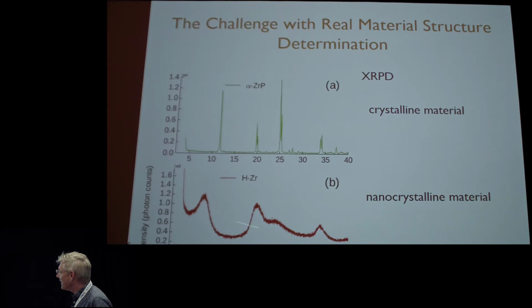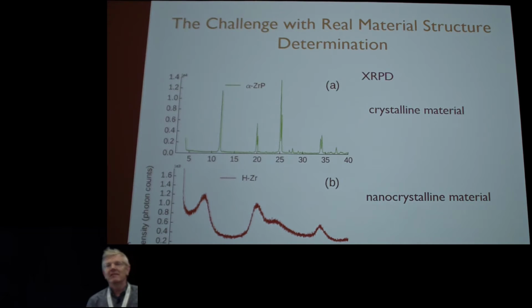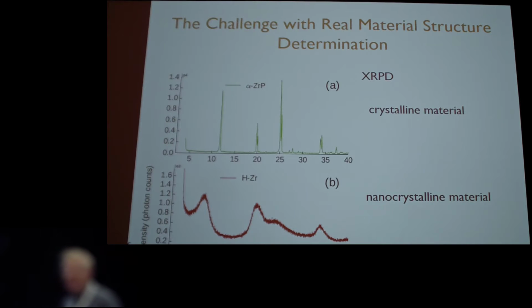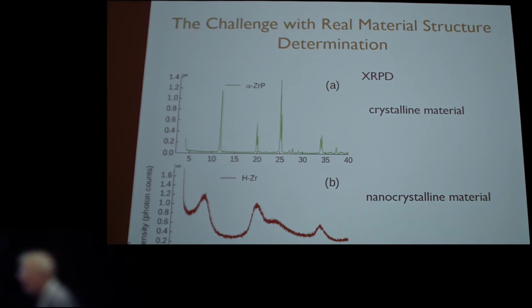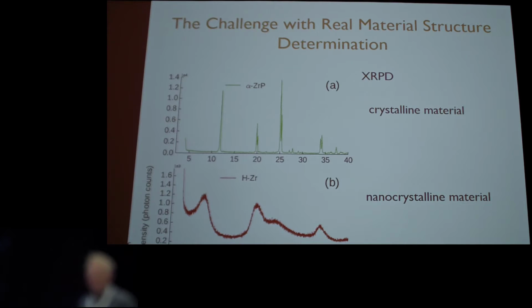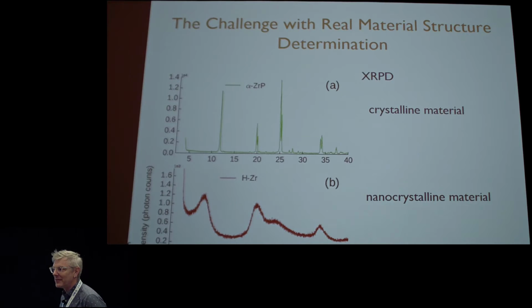How do you figure out, from an information theoretic point of view, how much information is in here? So if we assume these peaks are symmetric, which they may not be, you get roughly 3 bytes of information, 3 numbers from each peak: its position, its integrated intensity, its width. And so we have 1, 2, 3 well-separated peaks and 1 slightly overlapped peak. So we have about 12 bytes of information. So we can only really make a model that has 12 degrees of freedom and slightly less because we've got information loss here. So that would be a very simple model. And we have to avoid the temptation to overinterpret that data.